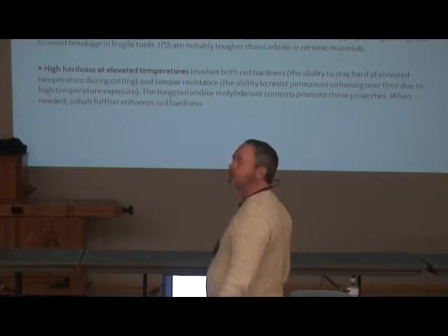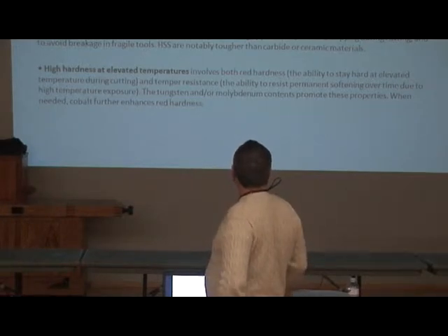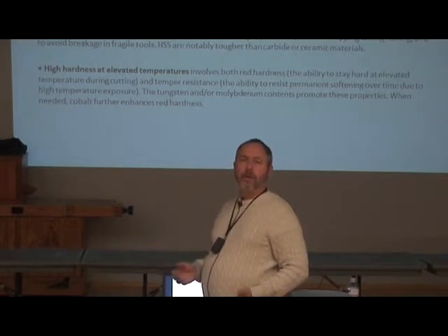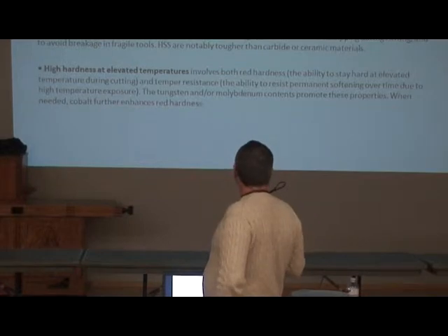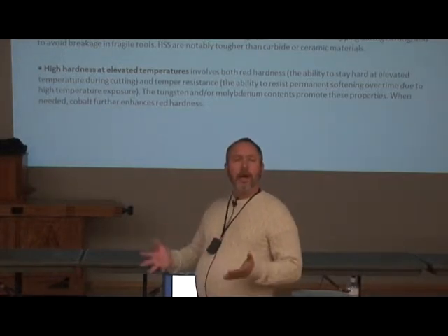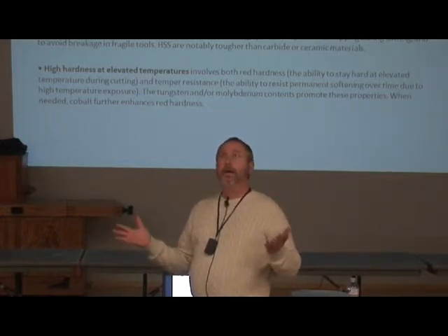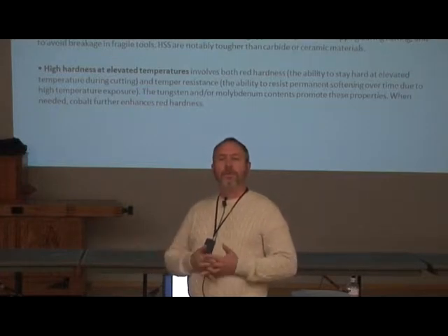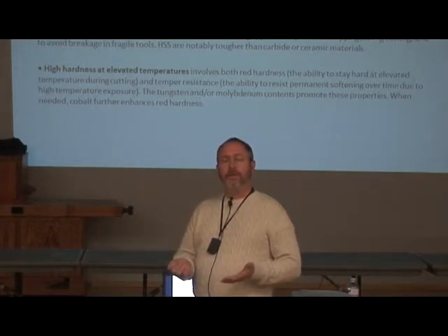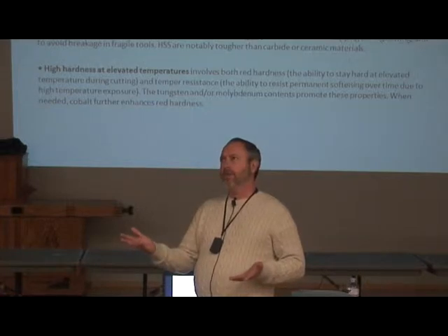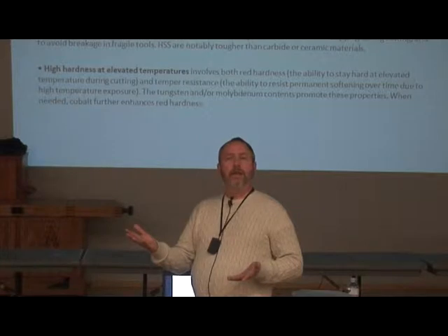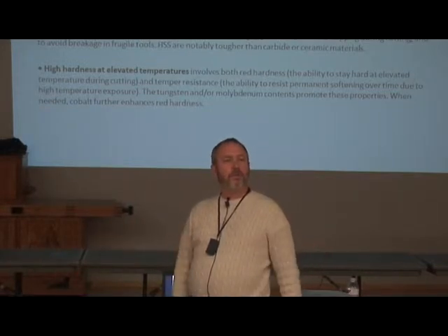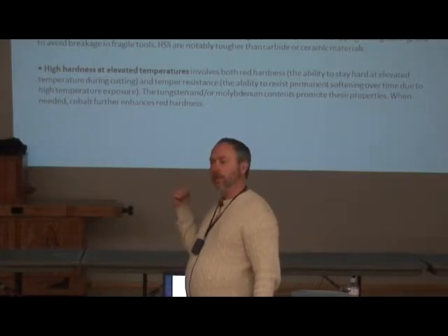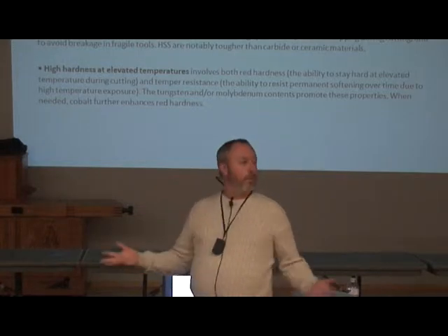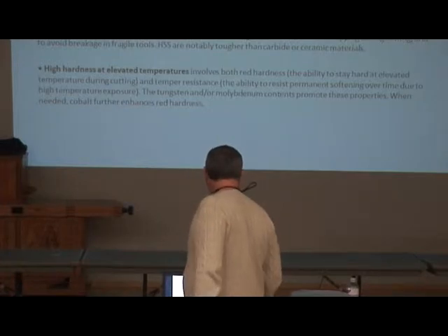It's very wear resistant, your high-speed steels. Depending on which one, they have impact toughness, and I'll go into some of the differences there. It also resists tempering at high temperatures. If you take a carbon steel, let's say a 0.8 carbon steel, harden it to Rockwell C60, and heat it up when you're sharpening it to a blue color, that's about 550, 600F, it'll go from Rockwell C60 down to 55. It doesn't resist the temperatures. Your tool steels are made to resist the temperatures, like these high-speed steels. So that's one of the reasons they've gone to your tool steels.